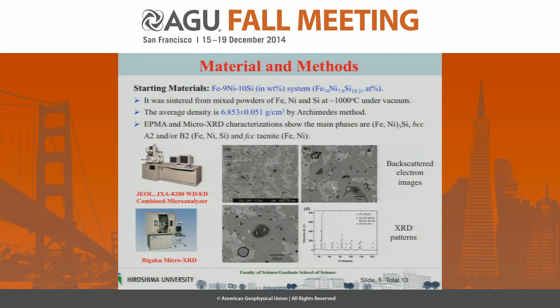We used a starting material of iron with 9% nickel and 10% silicon. It was sintered from mixed powders of iron, nickel, and silicon at about 1,000 degrees under vacuum. The average density is about 6.85 grams per cubic centimeter by the Archimedes method. We analyzed it by EPMA and micro XRD. These figures show the backscattered electron images and XRD patterns. Based on this analysis, we know our sample is mainly composed of Fe3Si, BCC iron-nickel-silicon, and FCC iron-nickel.